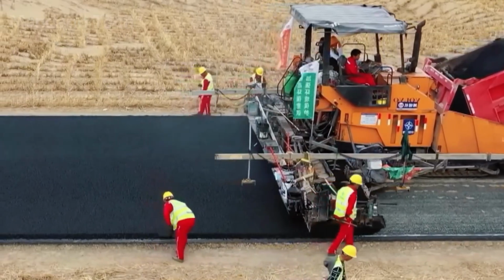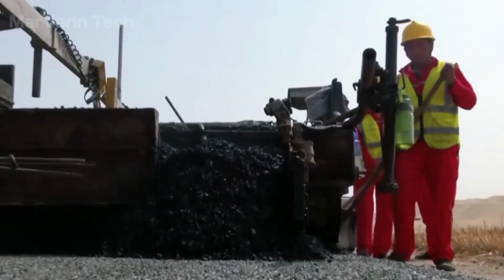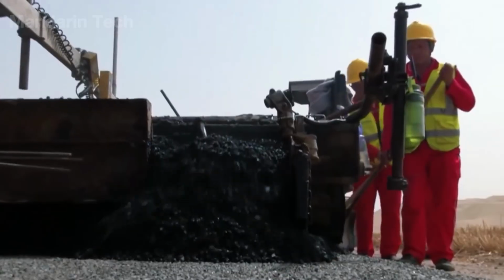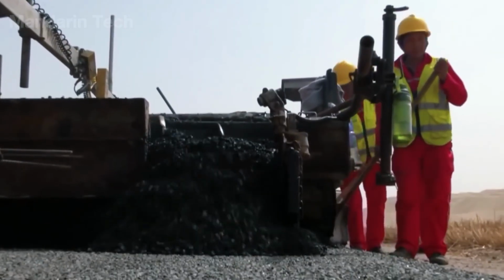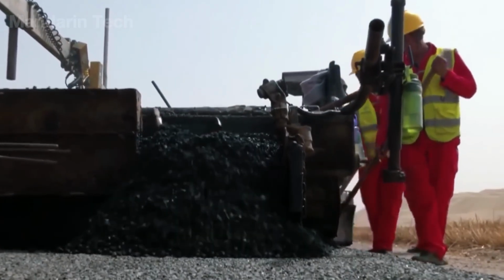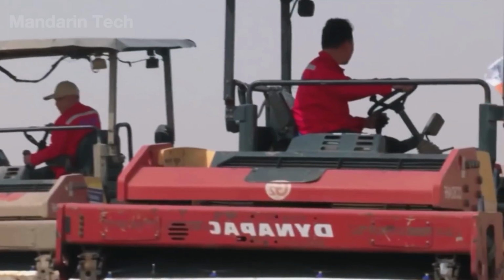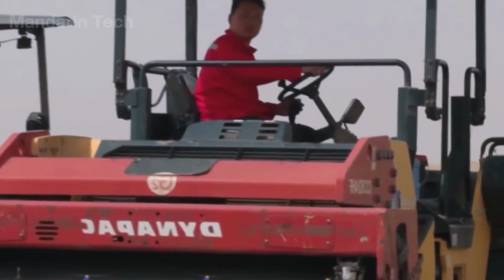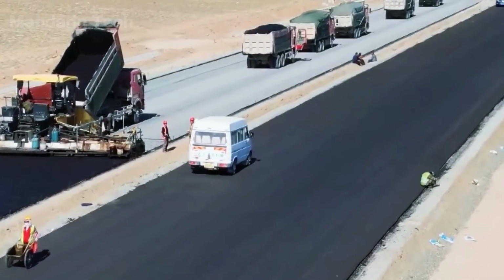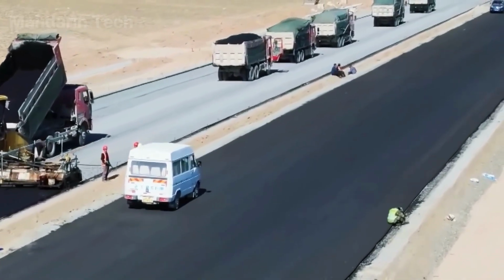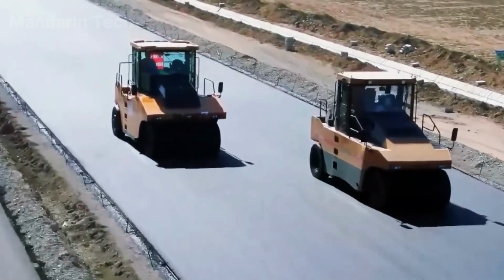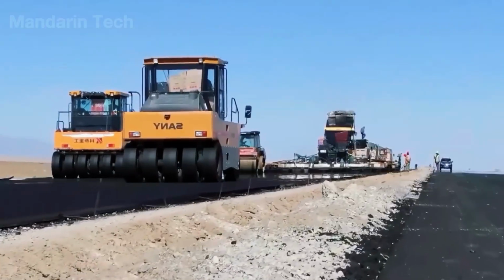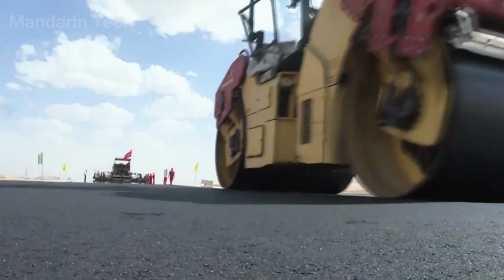Supervisors checked flatness with laser beams, allowing no more than 3 millimeters of deviation per meter. As the desert wind cooled the surface, the asphalt hardened into a flawless black sheet, tough enough to withstand temperature swings from -25 to +70 degrees Celsius. To finish, workers sprayed a protective seal coat, giving the surface its signature deep shine and locking out moisture.